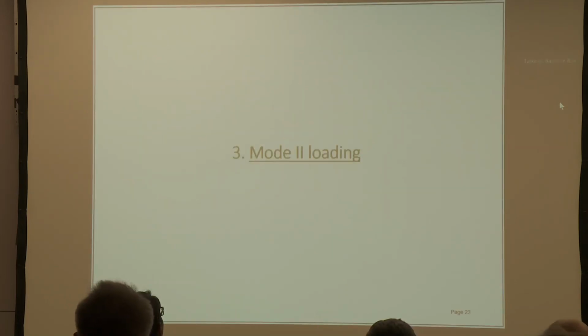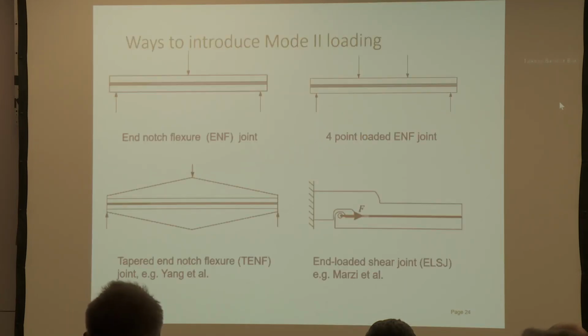So I want to end by saying a few things about Mode 2, which is currently a big work activity area for ESIS TC4 and for myself at Imperial. We know there are different ways of introducing Mode 2, and this is one of the challenges that whilst there was general agreement with how to perform a Mode 1 experiment, there are widely different ways of introducing Mode 2 to a specimen, from 3-point flexure to 4-point flexure to tapered end-notch flexure to, for example, an end-loaded shear joint.